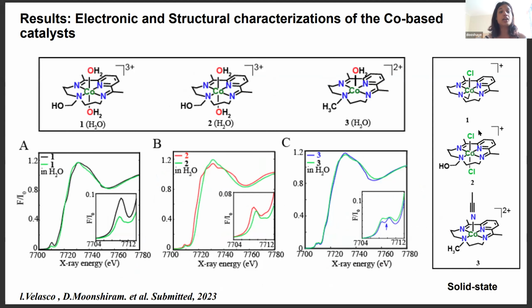The catalysts were then dissolved and incubated in water prior to time-resolved X-ray spectroscopic analysis. So upon dissolution in water, we see a shift of the pre-edge of all 3 catalysts, and expectedly catalyst 2, with the 2 chloride ligands exchanged with aqua ligands, shows a much larger shift in the rising edge. This is due to the disappearance of the 1s→4p plus shakedown contribution, as well as a change of its geometry from a distorted octahedral to a perfectly octahedral state. As well, the charge changes from +1 to +3.